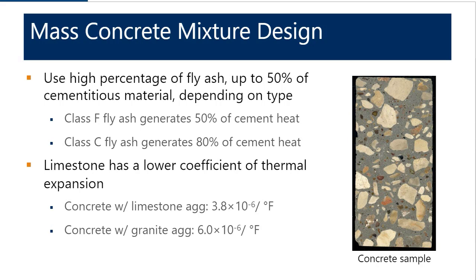In terms of temperature differentials and the risk of thermal cracking, the use of different concrete aggregates can also help reduce the risk of thermal cracking. In particular, limestone has a lower coefficient of thermal expansion than granite. And so if you have the option to use a limestone aggregate versus a granite coarse aggregate, because the concrete containing the limestone will have a lower coefficient of thermal expansion than an equivalent mixture that contains granite, the risk of thermal cracking can also be reduced through the selection of those lower coefficient of thermal expansion aggregates.